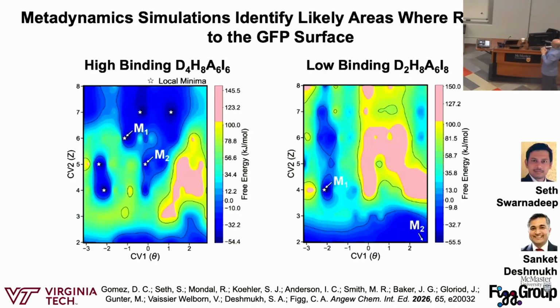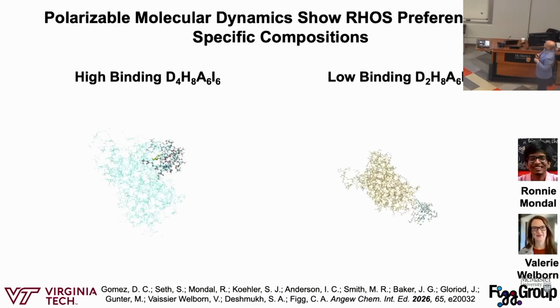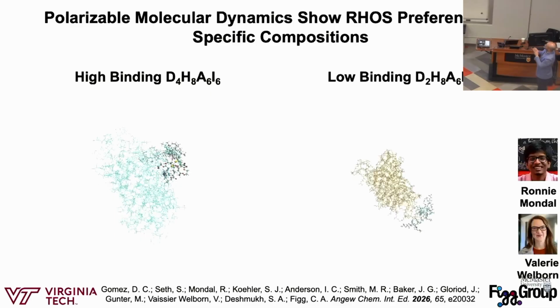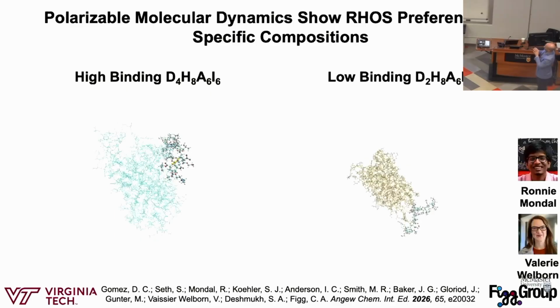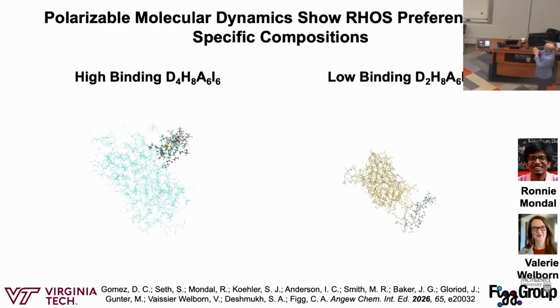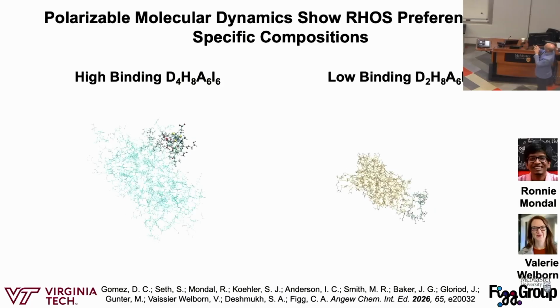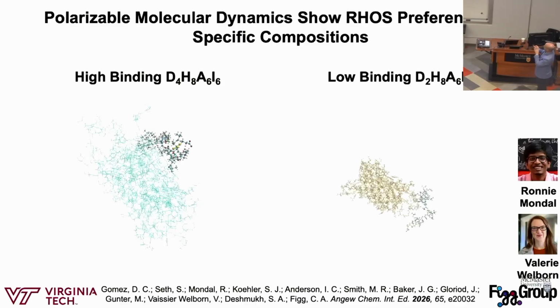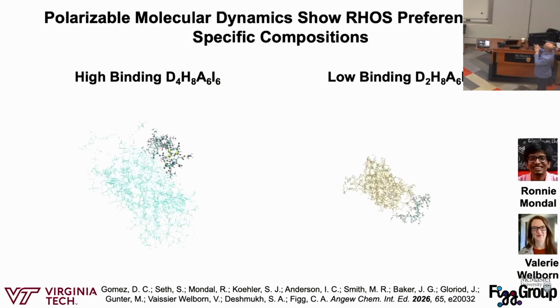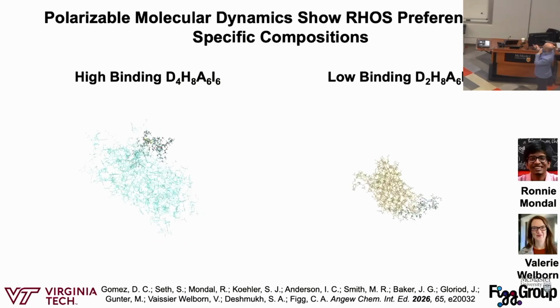Then what we did is we took these poses, because these are coarse grain, essentially putting a protein in a box, and then the oligomer moves around the box, and you can tell it not to bind somewhere. We took the poses from these and ran high-level polarizable molecular dynamics with my colleague Valerie Welborn. In this case, this is the high binder, so you can see the protein in blue. This is the oligomer, interacting on the barrel. This is the low binder pose from the last case where the protein is in orange, and the oligomer is down here at the bottom of the coil that I was talking about.